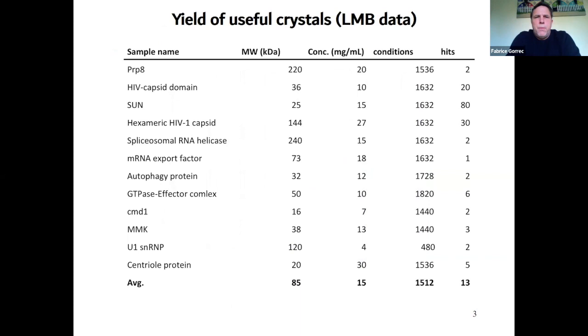Here you see some data from the LMB about the yield of useful crystals obtained against quite a lot of conditions during initial screens. So 1500 or 1600, plus 1800 plus conditions here. Despite the large number of conditions, we have a yield of useful hits of about 1%. And this is only cases where useful crystals are actually obtained. So there's a lot of cases where, unfortunately, you don't have any hits initially. So we could estimate that our initial yield is far lower than 1%.